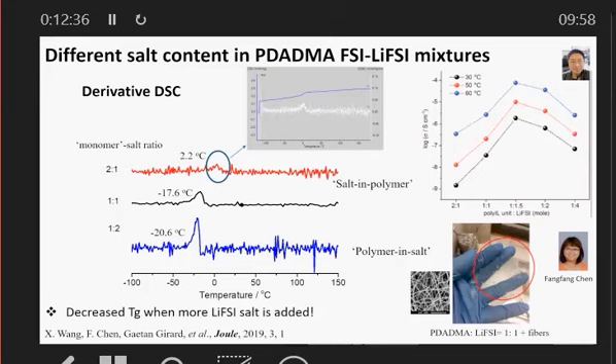Then we add the 1 to 1, the 1 to 2, so Tg goes down. And on this side here, we see that the conductivity is going up, but only to a maximum of about 1 to 1.5. As we go beyond that, we start to decrease the conductivity again, despite the fact that the Tg has still gone down. So this was a bit perplexing initially, and I'll show you why that is in a moment.